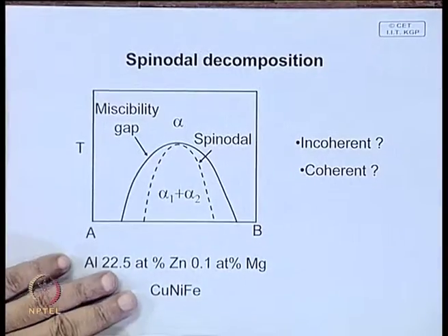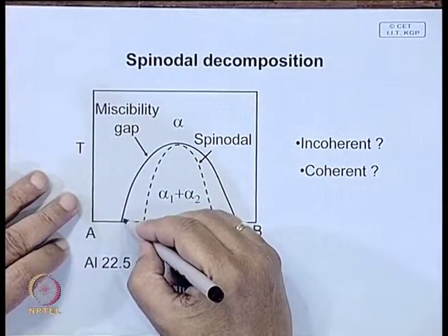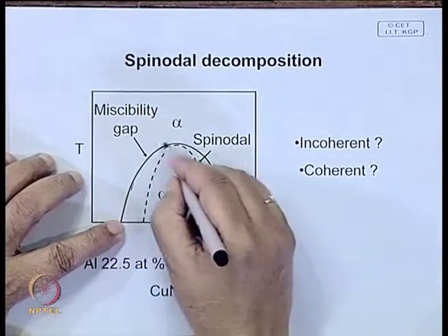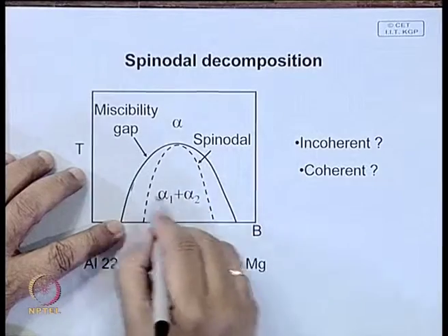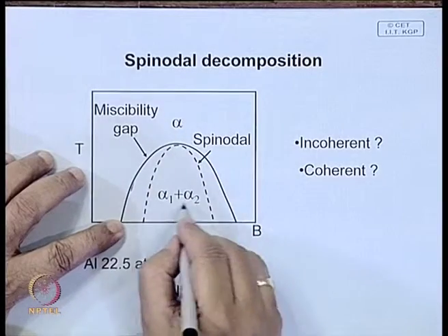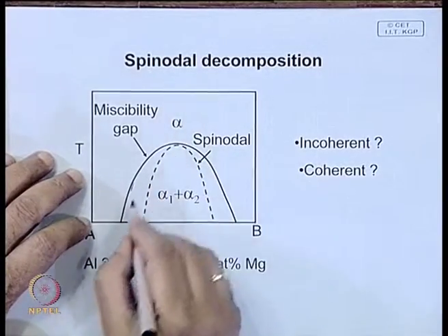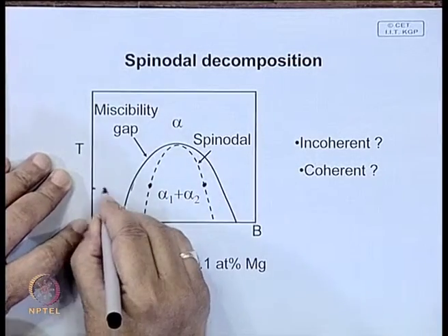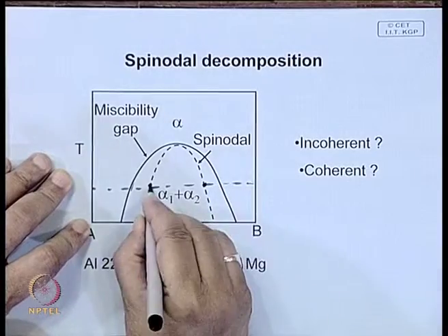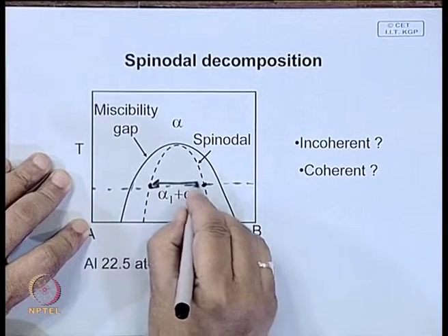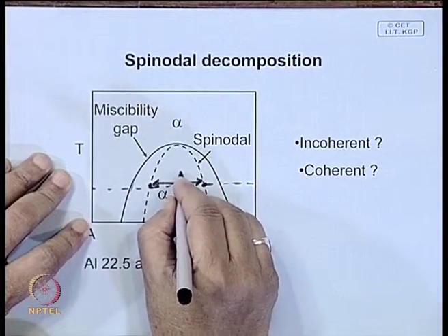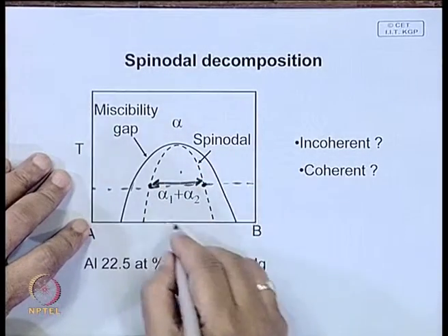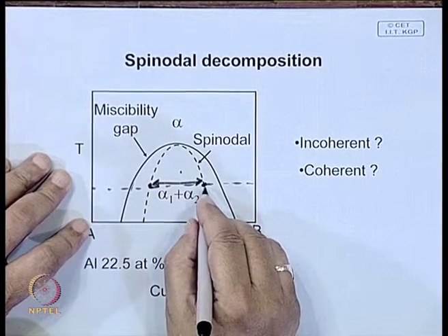So, if you have an alloy system, this is a spinodal, this is the solvus curve and here you have these two types of precipitation. It is possible to show this is the spinodal point at a particular temperature. So, within this you can have small fluctuation unstable, so within this you can have homogeneous precipitation, uniform distribution of precipitation.